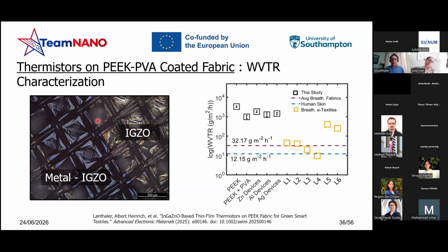How do we actually go back to the pristine, or try to achieve at least the same breathability as before? Well, the vacuum condition and the sputtering technique, since it's a physical bombardment of atoms and molecules onto the very fabric, might help. And actually, we saw that on all of the three devices. As you can see, the breathability decreases comparing the bare fabric to the coated one, but we were also able to restore, or at least aim to restore, the same breathability condition through the sputtering technique.